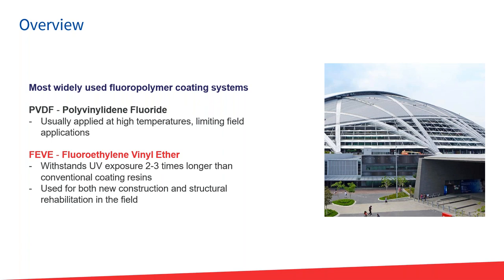FEVE came along and it kind of changed that, and it allowed for the usage of fluoropolymers in the field, because the chemistry of FEVE allows it to cure or cross-link at room temperature. So you do not need ovens to cure these materials. So that allowed now to do restoration, repaint, bridge coatings. Most bridge coatings are applied on site. So it kind of opened up some market spaces where PVDF was limited to allow for that same kind of weatherability with fluoropolymers.